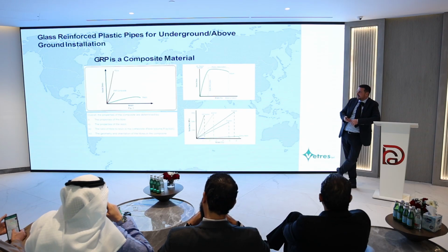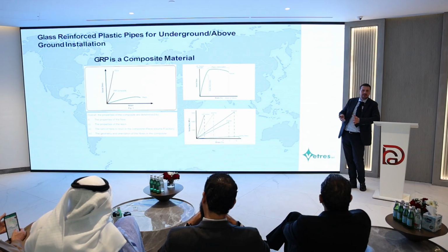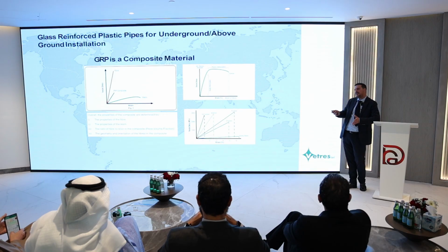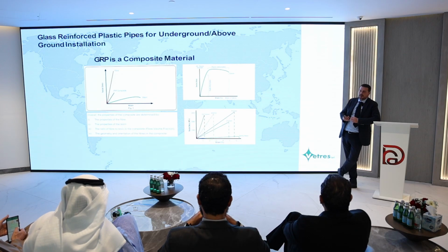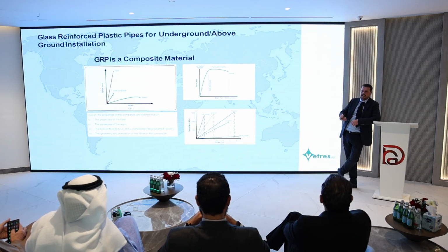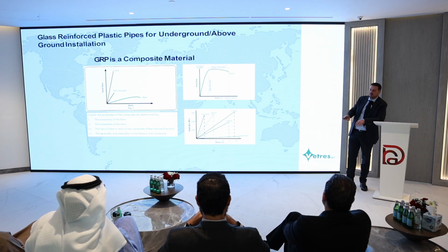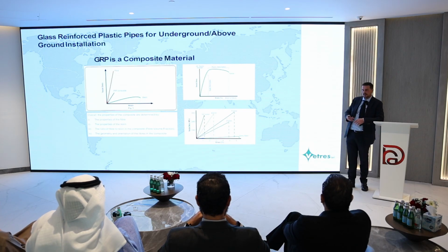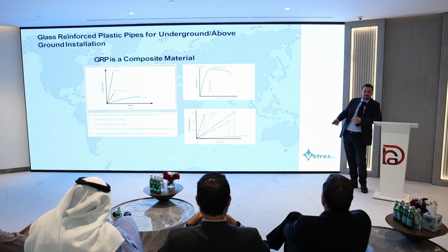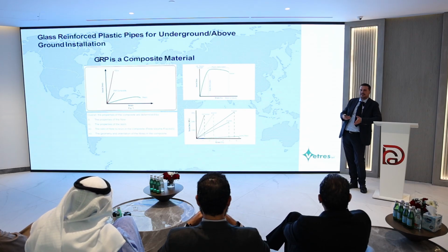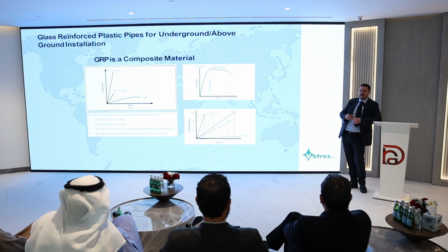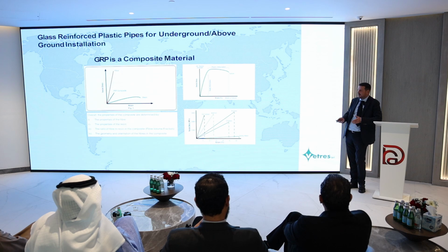GRP is a composite material that can today also reach mid to high temperatures, because before, GRP was used just for ambient temperature or maximum 60, 70, 80 degrees. Now with new resins on the market, we can also reach up to 140 degrees. Because the most important thing is the HDT of the resin, that means the heat distortion temperature of the resin. And now on the market there are resins with an HDT of 180 degrees, so that means that we can reach 140 with this kind of resin. Usually the most common resins used are vinyl ester, epoxy, and isophthalic resin, as I told before. Isophthalic resin is suitable up to 50, 60 degrees. Vinyl ester resin is suitable up to 80, 90 degrees. And then there are the epoxy novolac resins that can resist up to 140 degrees.